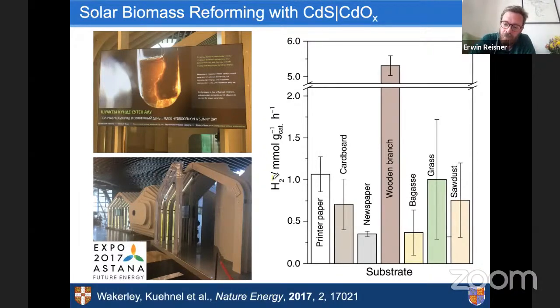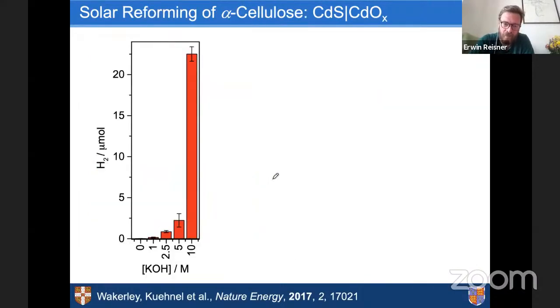But also, I mentioned before the alkaline conditions. And when I say alkaline, I mean seriously alkaline. Here's the activity of hydrogen against the molarity of potassium hydroxide. And 10 molar KOH is needed to really have very high activity.